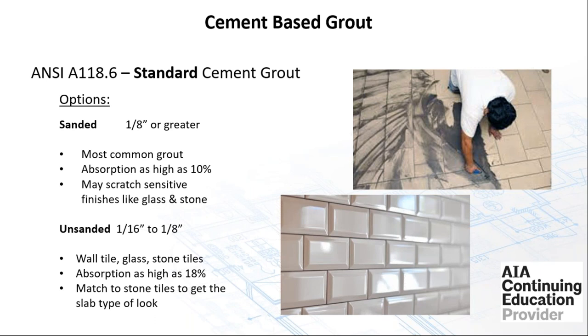What are your options? Basically two, sanded or unsanded. Sanded is 1/8 or greater, the most common grout, high absorption up to 10%, may scratch sensitive finishes like glass and stone. So like with any grout, especially these days with the beautiful glass and the stone tiles that we have, if there's any concern at all, do a small mock-up so you're assured that when the product gets on the job site, we don't have any issues.